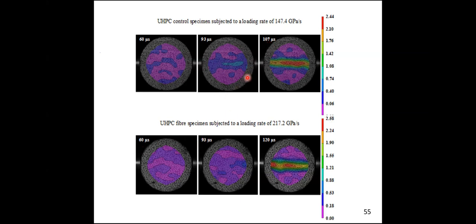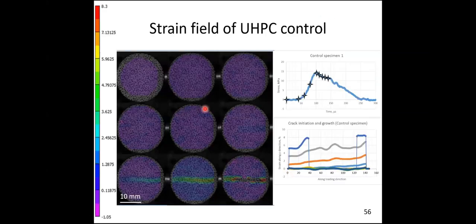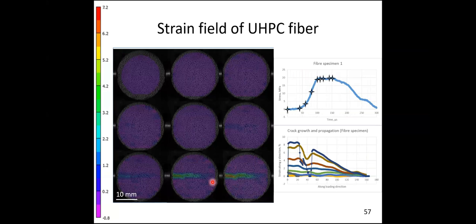Again, this is for one sample, this is for another sample. So you can see how the crack has propagated with respect to loading. This is what I wanted to convey. You can see here at different time steps I have given the crack growth. This is the final failure of the sample. Again here, this is for the other sample. You can see the crack is initiated, the crack is propagated, and finally it led to failure. So this is what I wanted to convey.